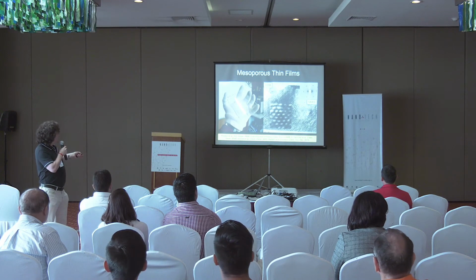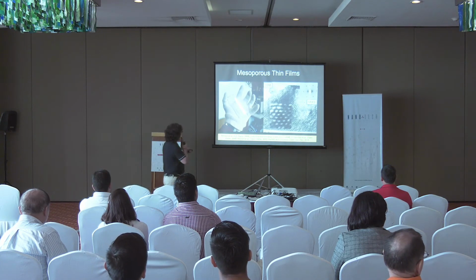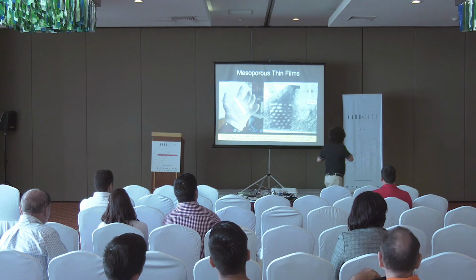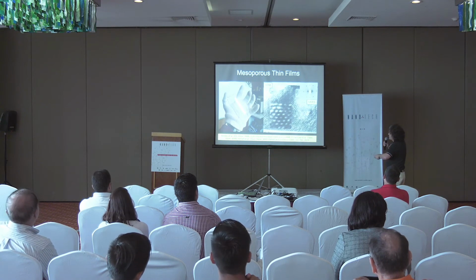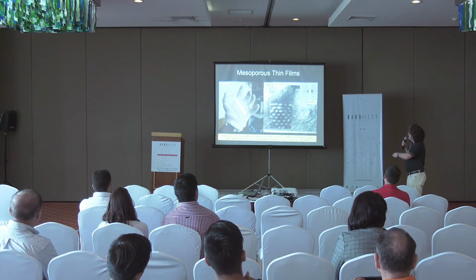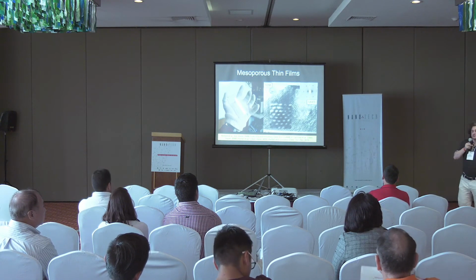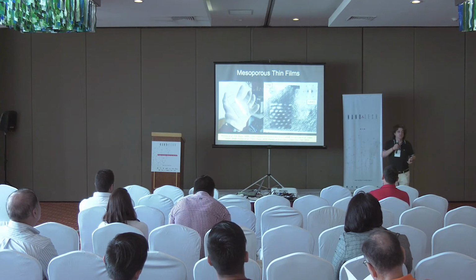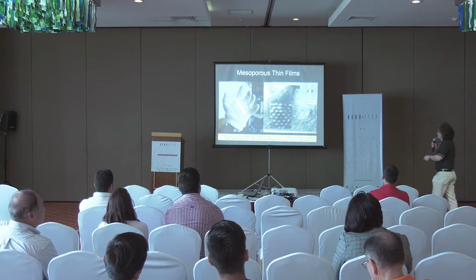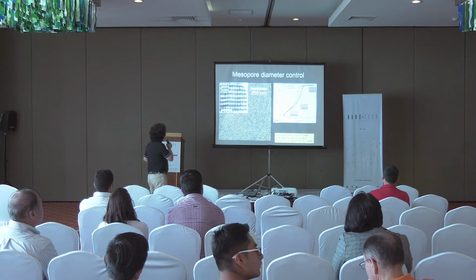We see this by transmission electron microscopy, but if you shine X-rays here, there is diffraction. There is diffraction at low angle. Why? Because you have periodicity in the electronic structure here, the walls, in the electronic density, and this periodicity is in the order of nanometers. So you have diffraction at low angles. And by identifying the spots here, and by indexing, you can, for example, retrieve all the symmetry of this network. And we know how to do it, and we spent a lot of time trying to understand what's happening. But now we are sure.